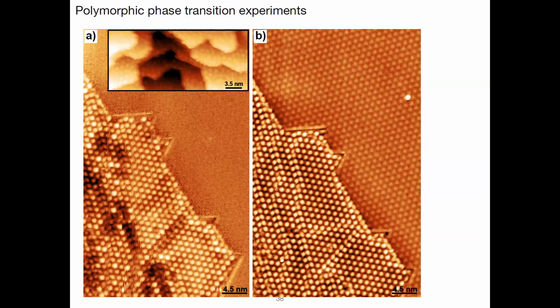Now, you mentioned that you were able to grow it on graphene and iridium. Which phase do you get, 1T or 1H? If you grow it at room temperature, you get 1H. There are some articles where, with a higher temperature, you can promote 1T. I haven't tried, but you can find that. And on HOPG, I found some areas of the islands that had a kind of dislocation, and I believe that maybe at some point when they were growing they were 1T and they changed to 2H or something like that. But you can grow both phases. The most stable one is the H.